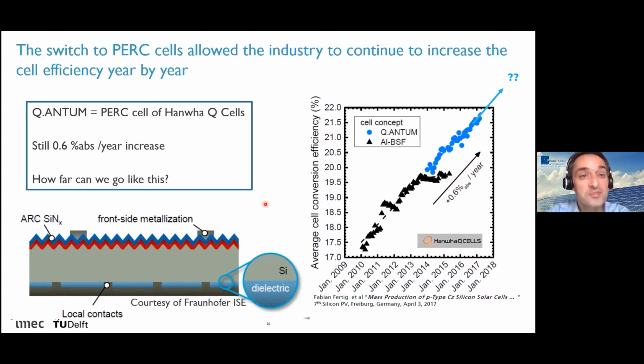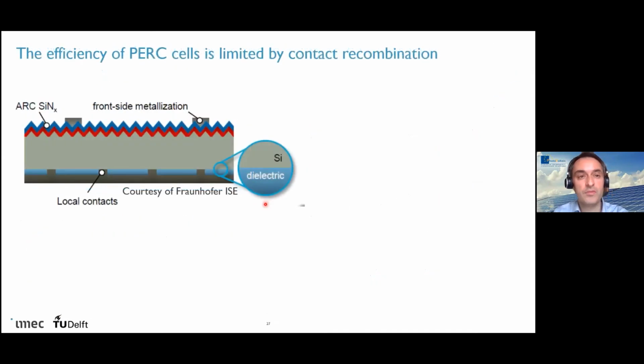But of course, this PERC cell now clearly has a much higher efficiency potential, but it will also be somehow limited. The question is, how far can we go with this PERC cell concept? What we find out is that the main efficiency limitation of the PERC cell is the rear surface recombination. We only have a few percent, let's say 3-4%, of the surface in direct contact with aluminium, but this 3-4% is still the weakest spot of the device.